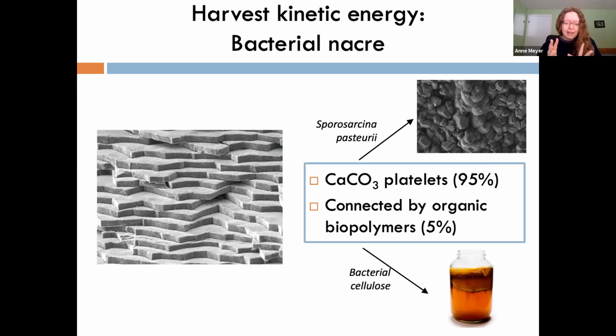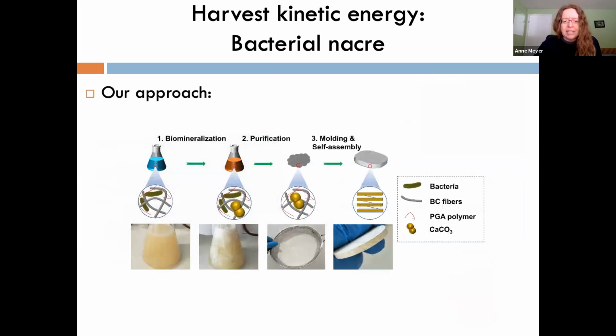So here's a specific kind of bacteria where the longer you grow it, you see on the top of our tube there's this thick layer, and that's bacterial cellulose. So it's very easy to produce a large amount of cellulose. You just brew some green tea, add the bacteria, let it sit and grow, and the longer you wait, the thicker and thicker this cellulose layer grows. So that's the polymer we're going to be harvesting to make our nacre with.